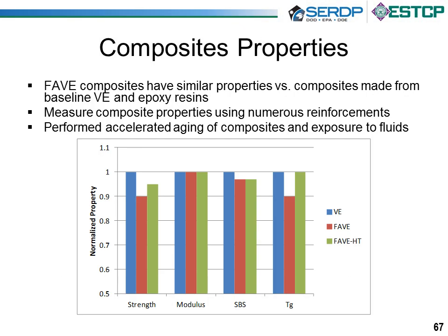The blue bars show the vinyl ester with styrene, and that's what we normalized all the properties to, so they're all normalized to one, as you can see. And you can see that the fatty acid vinyl ester shown in red has either a slight knockdown or about the same property as that of the vinyl ester. And we can go to this FAVEHT shown in green to improve the properties a little bit more, but there's a slight knockdown in the performance relative to the standard vinyl esters.